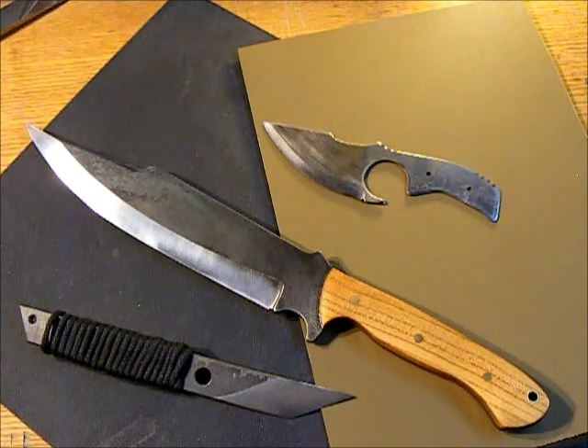Now I found if you want to get between 60 and 62 HRC, it's a double temper, usually 2 hours per inch of thickness. So I think usually 2 tempers at an hour, let's say 450 degrees, will give you 61 HRC. So, I did shoot a little video of my forge and actually hardening the steel. If you notice when I pull the blade out, I don't stick it on a magnet. That's because it's been soaking at critical temperature for that 7 minutes. So after that, threw it in the oven and tempered it twice and did a little flexibility test.